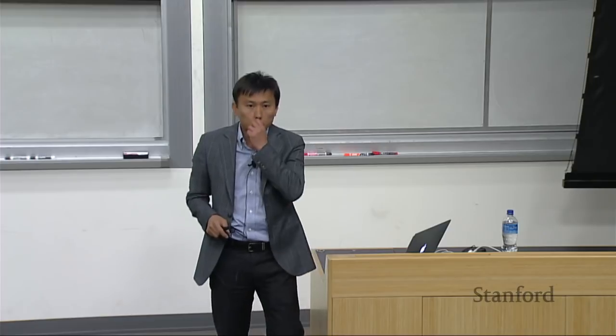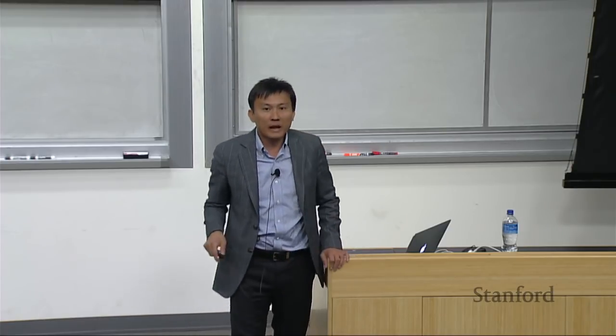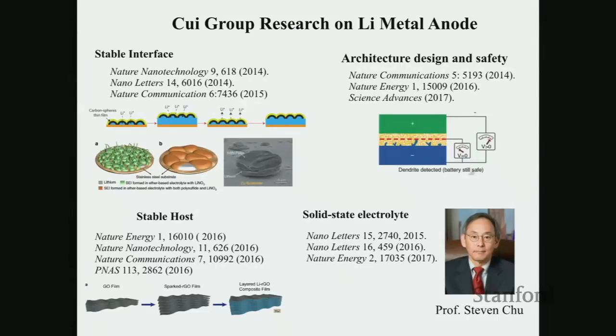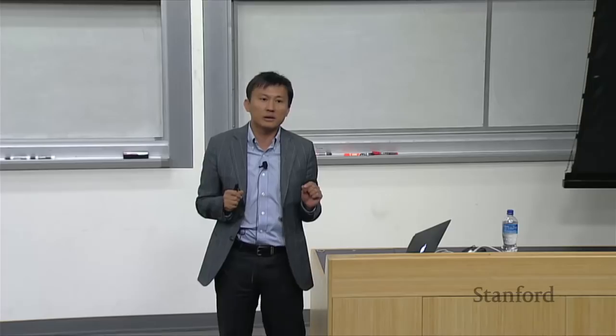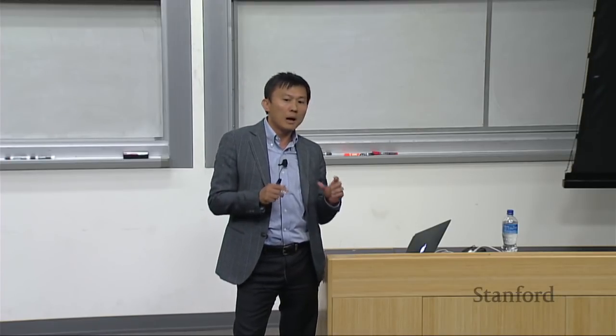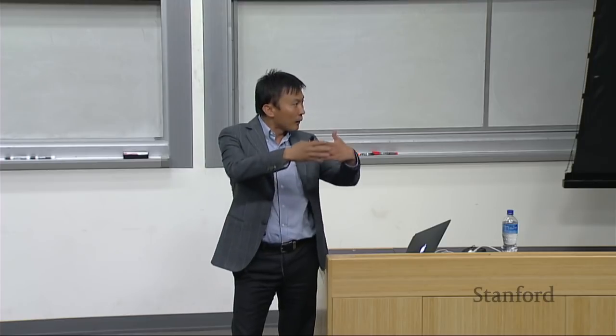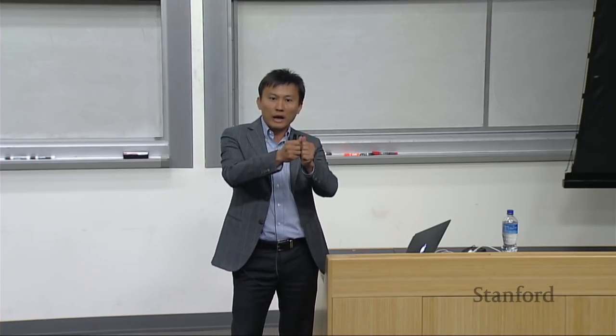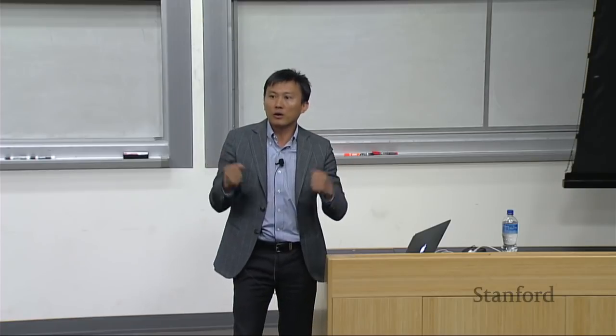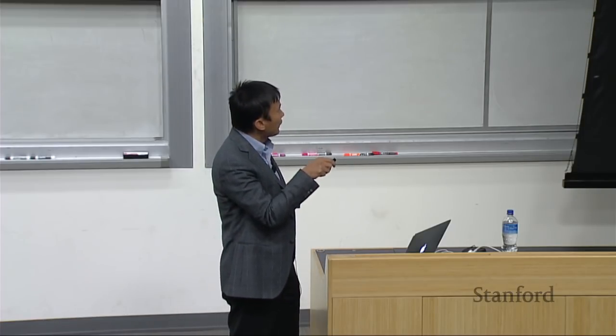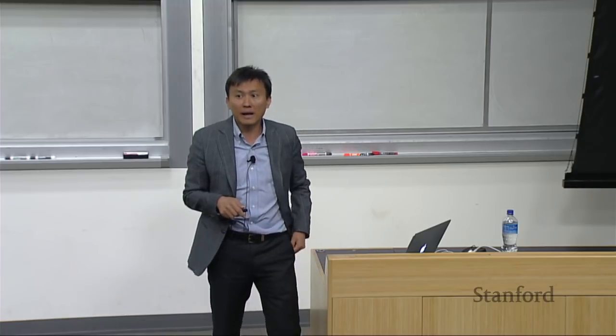About 5 years ago, Steve came back to Stanford. He and I had a meeting. We brainstormed a lot of ideas. How do we solve this problem? So we came up with a strategy. How do we stabilize the interface to overcome the high chemical reactivity problem at the interface? We also pointed out to the community that not only does it need to be chemically stable, at the same time it needs to be mechanically stable. Otherwise, with plating and stripping, you keep changing your interface, putting a lot of stress onto it. You had better find an interface that's chemically and mechanically stable.